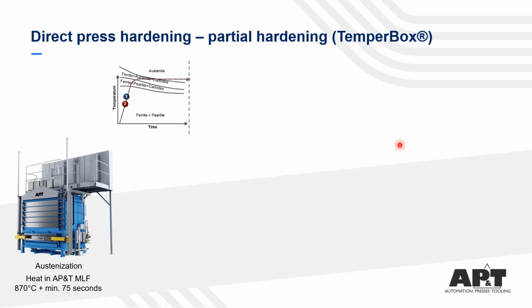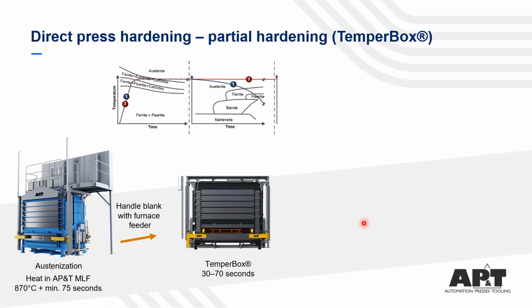Similar to the direct process we have an austenitization, here in an example of a multi-layer furnace. That's our own product. This is the new product basically, where we combine conventional multi-layer furnace chambers, 5 pieces of them, with a temper box in the bottom of the furnace. You will see some product pictures later on as well. So we have the austenitization. After the austenitization, we transfer the blank into the temper box. And depending on the final mechanical properties that you would like to reach, and depending very much on sheet thickness, we have a time inside the temper box that varies roughly between 30 and 70 seconds.